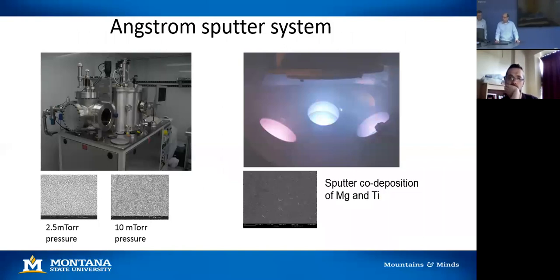Next tool is the Angstrom sputter system. Unlike the evaporation tool, you don't heat the target material directly to get vapor coating your substrate. In this case, you actually hit your target material with argon ions, and they ballistically eject that target material out into the chamber, and then that coats everything in the chamber. Over on the right side, we have two RF sources and one DC source inside the system, so you can run all of these independently or at the same time, depending upon what you're trying to deposit.